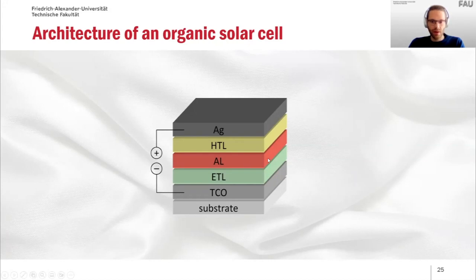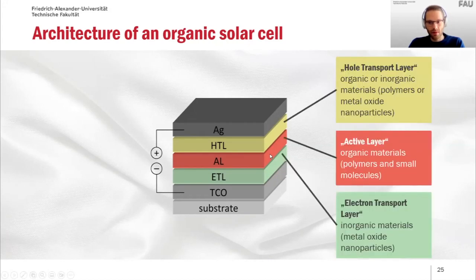So in the center, we have an active layer, the active material, which is organic. That's why it's called organic solar cell, which is usually a polymer or a small molecule, so carbon-based materials. And this absorbs the light, the photons, and converts them into positive and negative charges, which are then directed by a hole transport layer and an electron transport layer on the top and below this layer. So the one lets only positive charges pass and the other one only negative charges pass, so that we can extract the current out of the solar module.